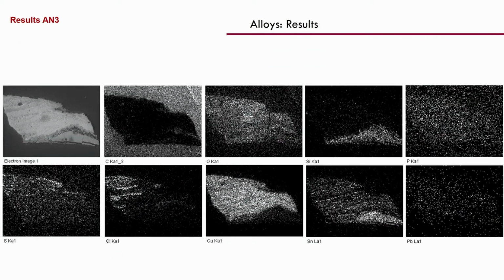As you can see, this is a mapping that we performed. You see the elements here. You can see copper, for instance, that is present in all the cross section, and of course tin. So this is of course bronze, and you see that we have phosphorus coming from the bone, and we have in every sample chlorine that comes from the ground, because we are close to the sea, of course. So in almost all the samples, you will see the chlorine element, often associated to sulfur. So probably a sulfate or something like that is present in the material.